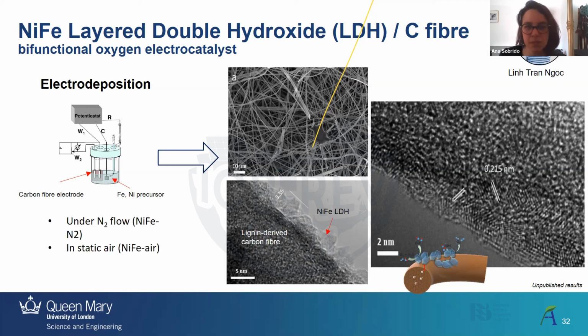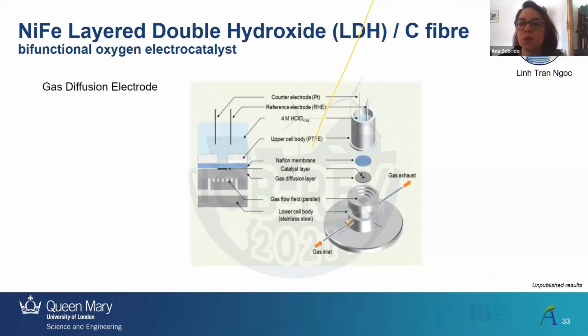What we do is change the conditions a little bit, to see what happens when you modify the parameters. We did one under nitrogen flow, and then another one in static air. So this is called nickel iron N2, and this nickel iron air. To characterize these materials, we use a gas diffusion electrode, in collaboration with the University of Copenhagen. What we do here is put our catalyst here. This is very handy for us because usually, to characterize a material for oxygen evolution or reduction, you use a rotating disc electrode.